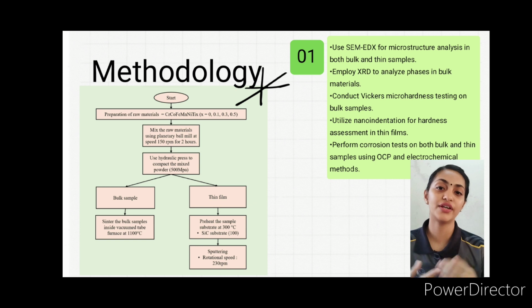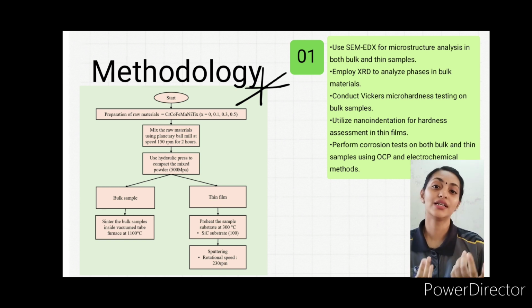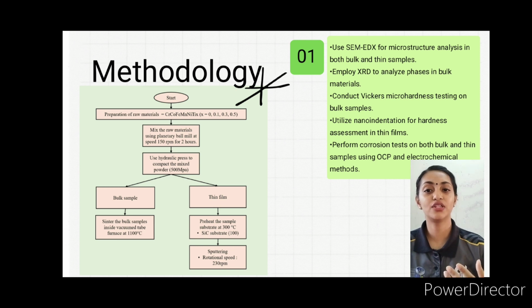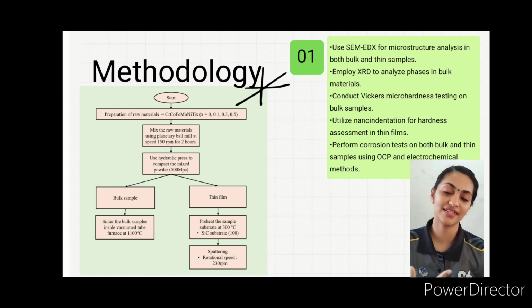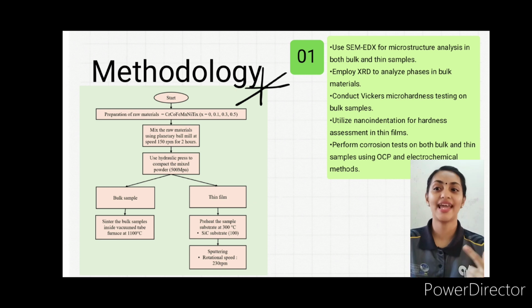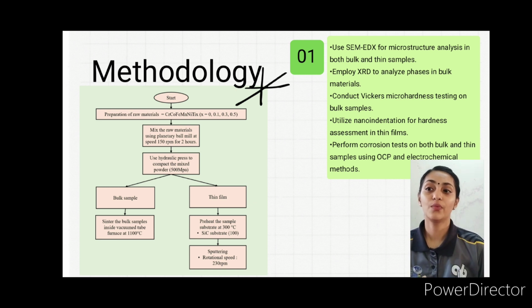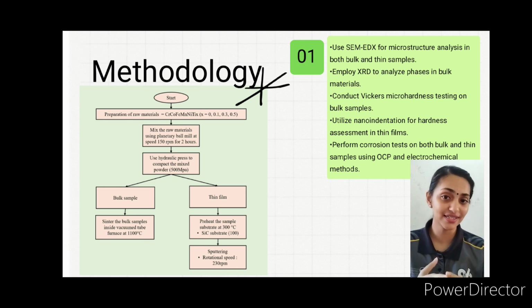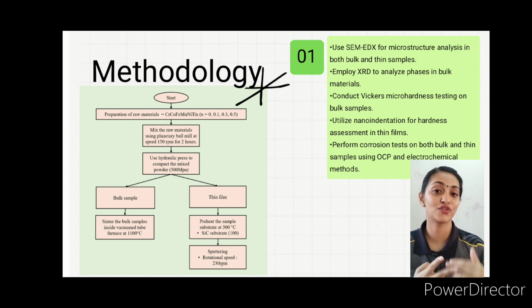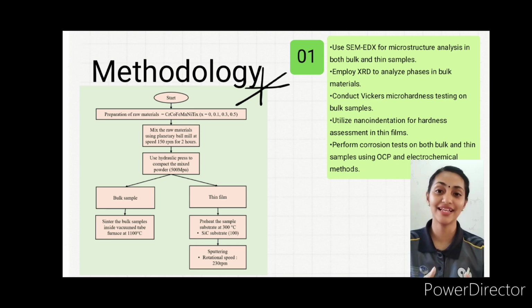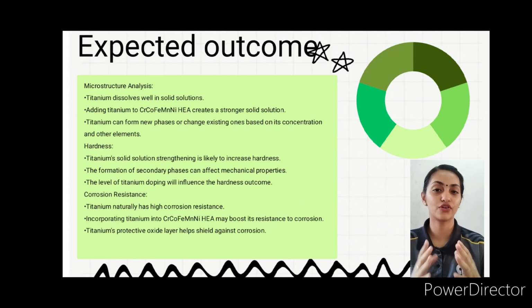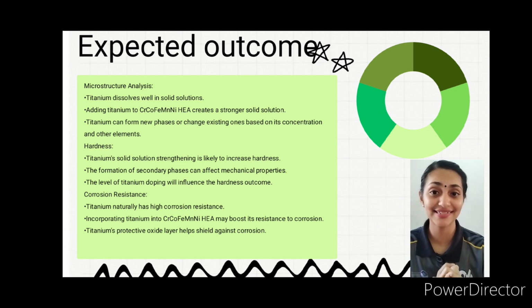For thin film, I will use radio frequency sputtering. First, we will preheat the target, which is the silicon substrate, and next we will use the sputtering with a rotational speed of 230 rpm. For testing, I will use SEM and EDX for microstructure analysis, XRD to see the phase changes, and Vickers microhardness testing to look at the hardness of the bulk, and also nano indentation to look at the hardness of the thin film. And finally, we'll run corrosion tests such as open circuit potential OCP and also EIS for both bulk and thin film.